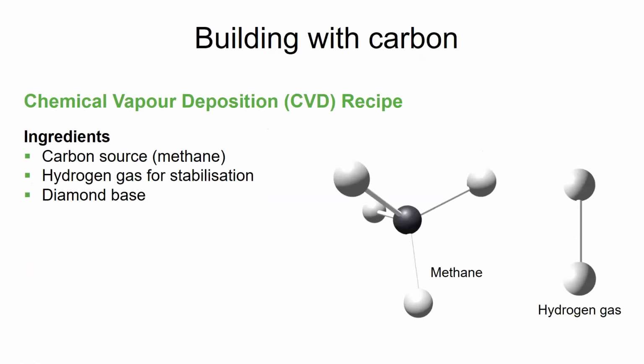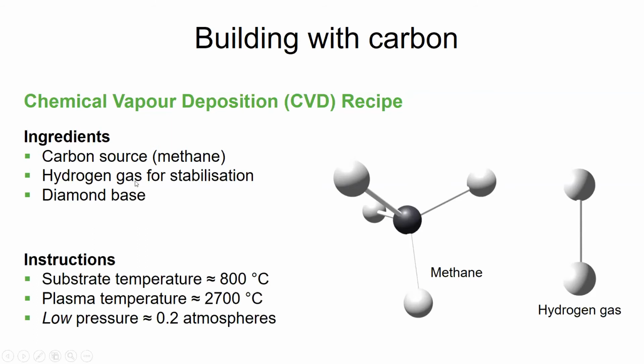However, people now have realized there are far simpler ways to grow diamond and with better control in terms of changing its physical properties. And actually, I said the way to grow nanotubes and to grow graphene is to use these hot ovens. And we do exactly the same here, except we're also combining it with microwaves to produce these high energy plasmas. We have a carbon source, we're going to pump methane in, we have hydrogen gas, and we have a diamond substrate to grow off. And if you look here, you can see that the substrate temperature is much lower. The plasma temperatures, because we're using a microwave to generate a plasma, is high, but the pressures are much lower. So this is a more manageable system.